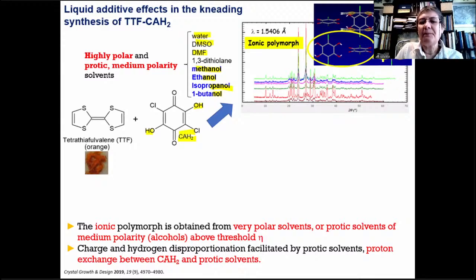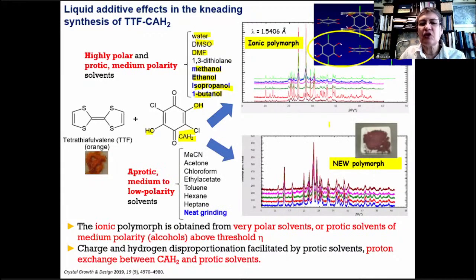So this transfer of hydrogens and charge may be facilitated by these protic solvents, the alcohols, that may actually support the transfer, or they may exchange hydrogen with chloranilic acid molecules, and that way support the formation of this ionic polymorph. So when low polarity solvents and no solvent are used, then we obtain a new form, which is the same color as the ionic form. It is not distinguishable by color, but its powder diffraction data is different.